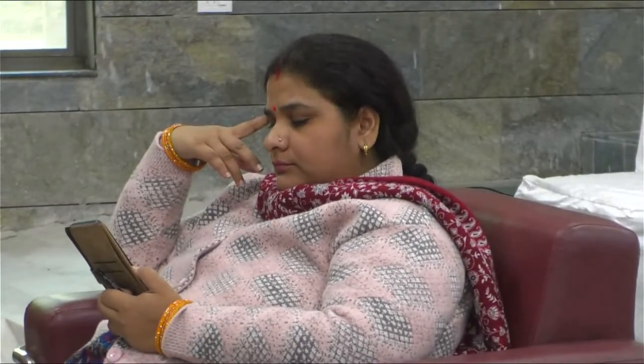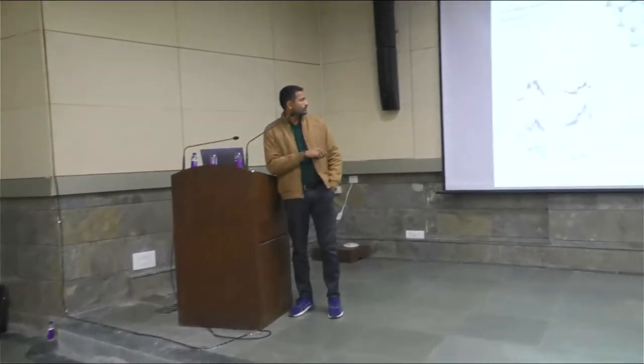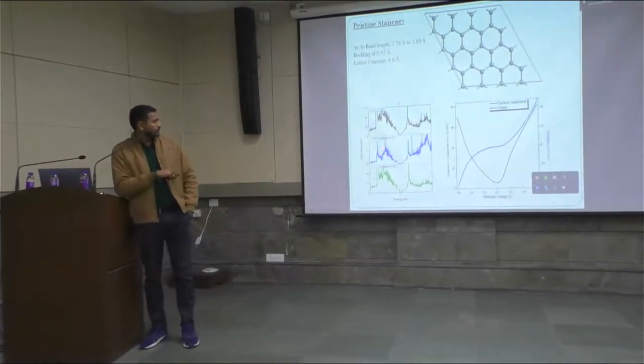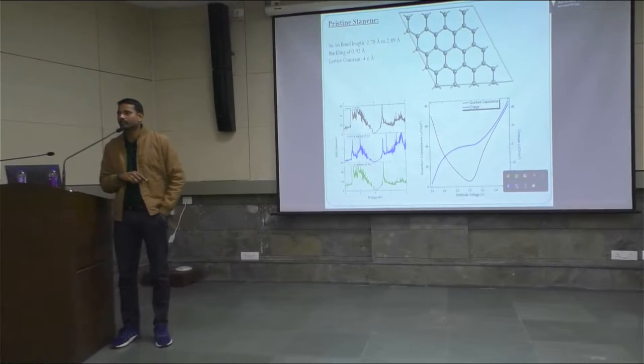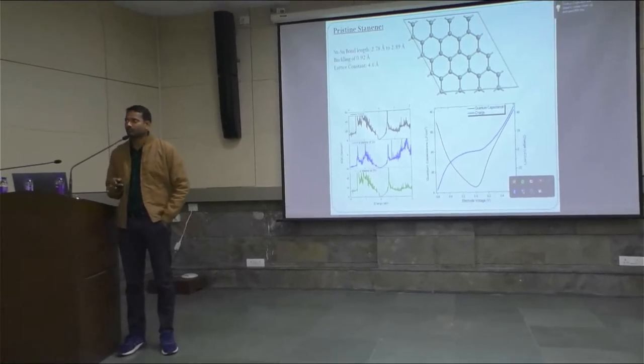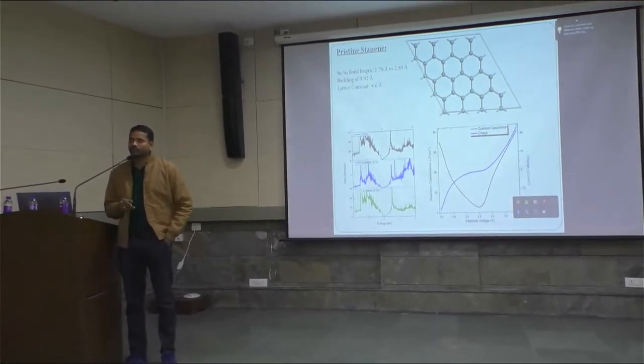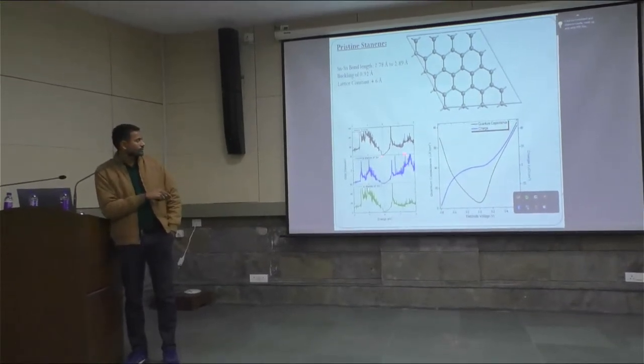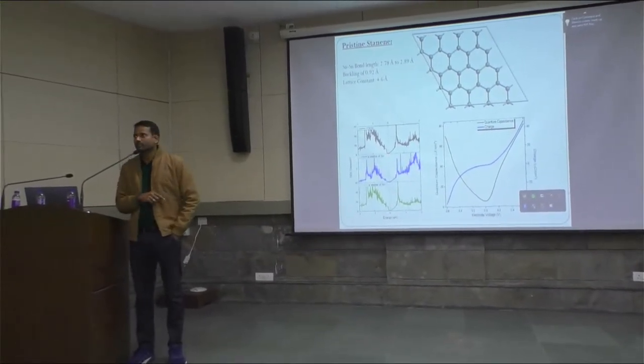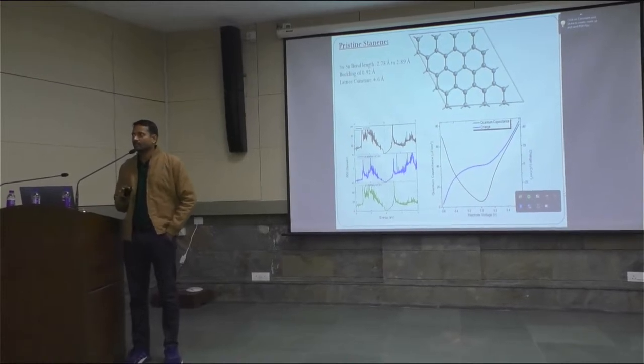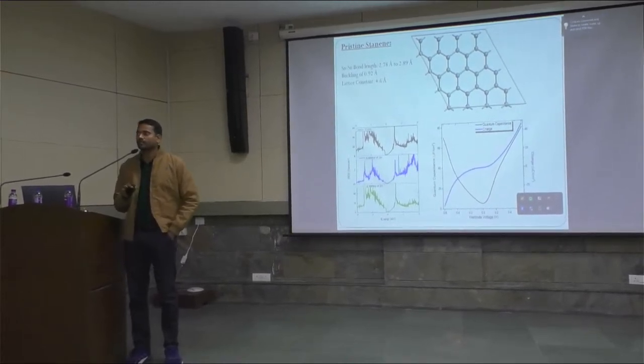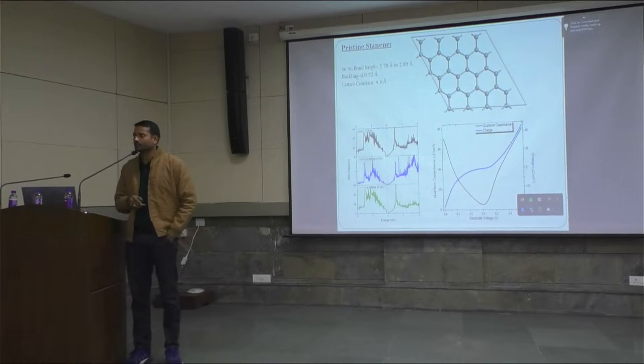First, I have analyzed the pristine stanene. In pristine stanene, we first extracted the density of states, and we have confirmed that stanene also offers zero band gap, just like graphene. But the p-DOS shows there are s states and p states. If you look at graphene, we know there are specifically s states for pristine graphene because of the sp2 hybridization. But in stanene, we have both p states and s states, and the presence of p states indicates there is sp3 hybridization also. And the report says stanene has coexisting sp2 and sp3 hybridization.